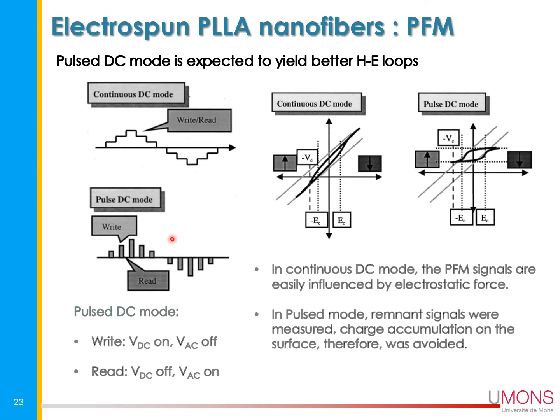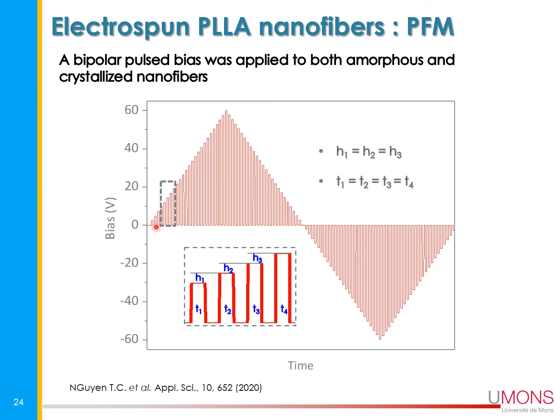So that's why it was introduced that you are poling the sample, you are writing something, and then you measure when the DC is off and the AC is on. So it means that you have different steps, writing and reading. Instead of having this, which is not the actual value that you are expecting because there is a contribution of the electrostatic, it's better to have this kind of shape which corresponds to the pulse DC mode. This is what we use, and this is, for instance, the evolution of the bias versus time, and you can see that with that we have different steps, and we are measuring always in this situation.